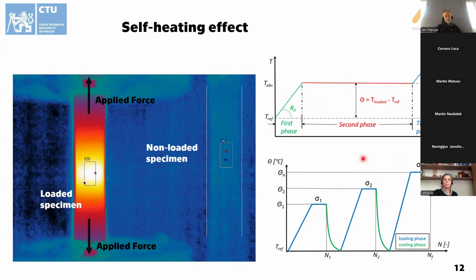What we were trying to do was to find out the stabilized temperature, to focus on the stabilized temperature for further use. So we designed a step test. It means that we were inspired by the step tests done previously in different papers, although we were using different materials, to set up how many cycles per block are necessary to find out the stabilized temperature, as the stabilized temperature is a variable with the amplitude of load.